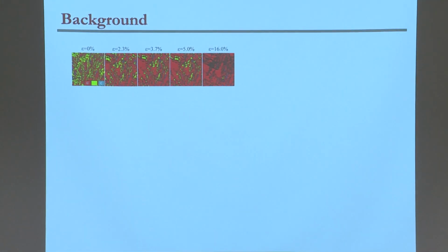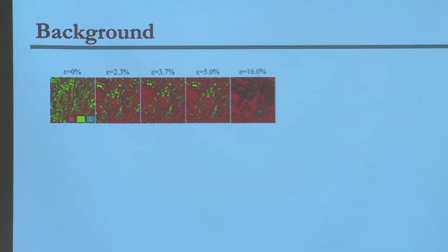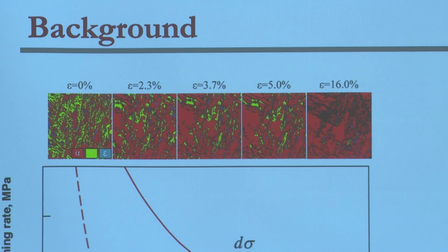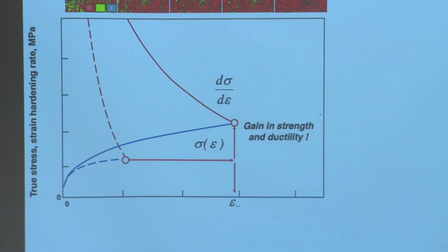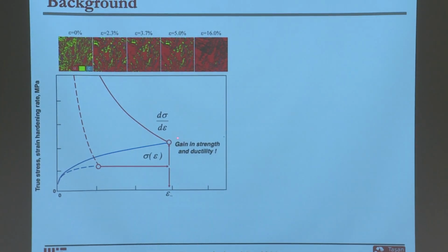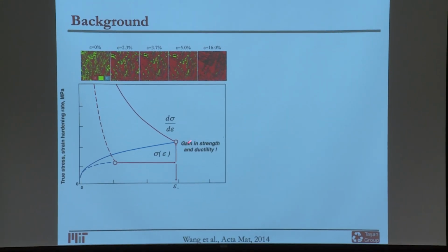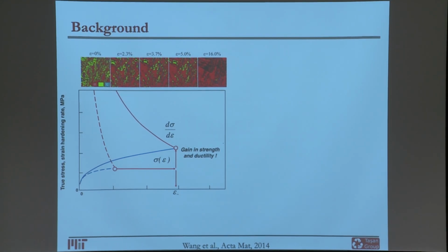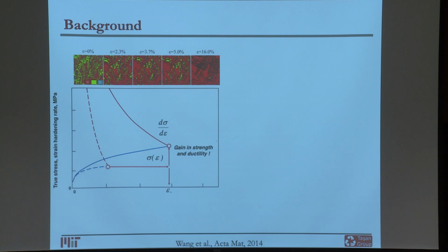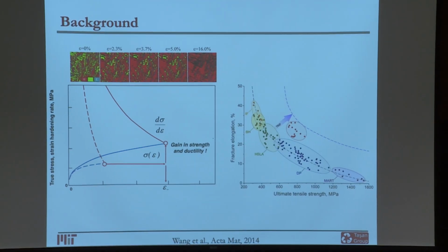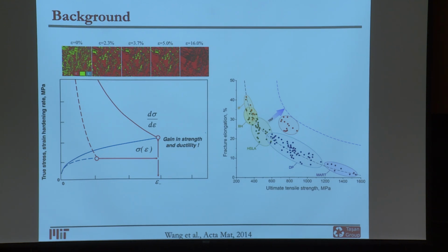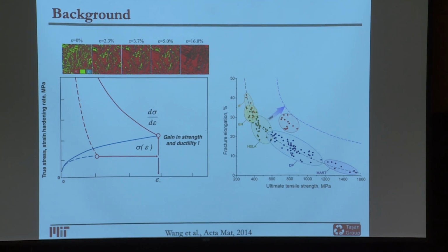The problem here is the following. We want martensitic transformation because it gives us many benefits. We get the TRIP effect, we get a toughening effect, we get ductility. For instance, having deformation-induced martensitic transformation increases the strain hardening rate, and that gives us essentially increases in both strength and ductility. You can make materials that are both strong and ductile. However, this kind of transformation also has some disadvantages. As a result of this transformation, you are also introducing a phase that is a little bit prone to damage and failure. So the martensite that is introduced is actually a typical damage site when you further deform this material.